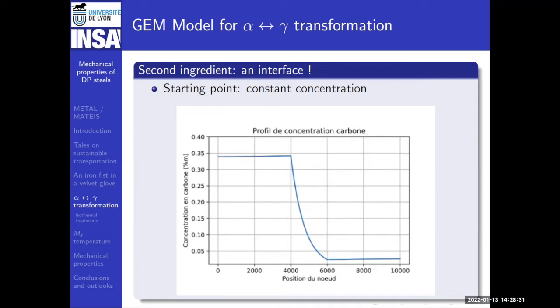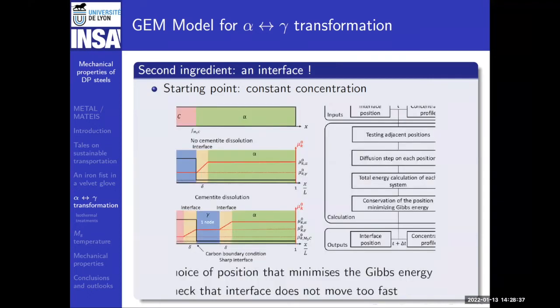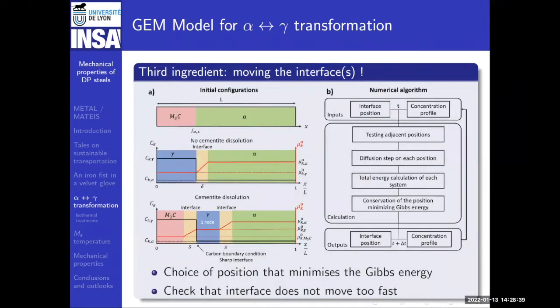Third ingredient: now we want this interface to move. To make this interface move, we start with gamma here, the austenite, and alpha, the ferrite, and we move the interface in the direction and with the amplitude that minimizes the Gibbs energy.